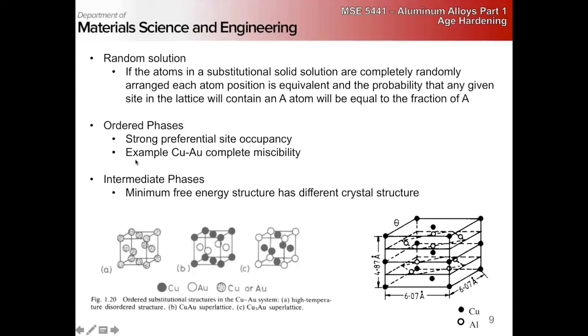We can also have ordered phases, right, where we have a strong preferential site occupancy. For example, copper gold has complete miscibility, but they form an ordered structure by layers, right? So we have a much higher probability of finding gold and copper on different sites of the FCC lattice, right? So here we have the copper gold, and here we see the copper 3 gold, depending on the composition of the structure.